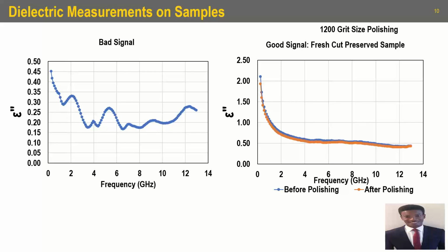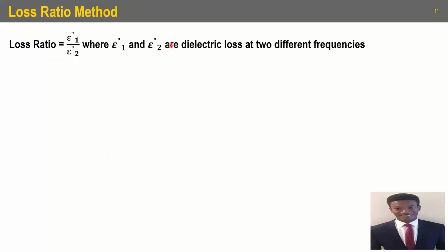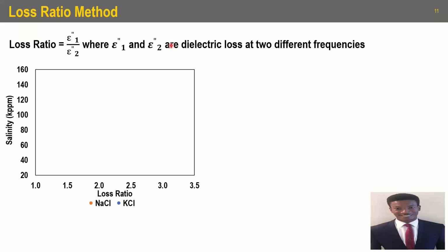Based on this, I then introduce the loss ratio method, which is our newly developed methodology for salinity determination. So what is this loss ratio method? It's actually a ratio of the dielectric loss at two different frequencies. And so we see salinity as a function of the loss ratio for NaCl bulk brine solutions and for KCl bulk brine solutions. We pretty much see that they agree with each other. And we see that even just for a salinity range of 20,000 ppm to 160,000 ppm, we have quite a vast and dynamic range of the loss ratio.